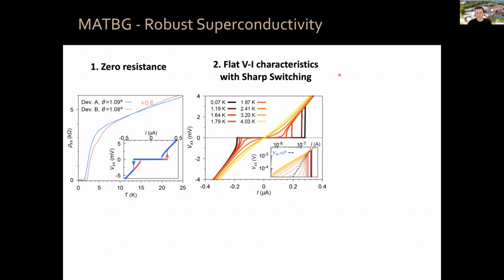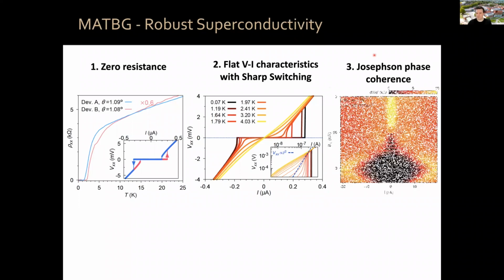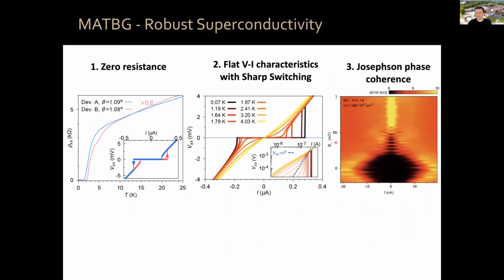And then the last thing, which I think perhaps is one of the most important ones, is that you should look for Josephson phase coherence. If you measure the critical current as a function of perpendicular magnetic field in these devices, because there is a little bit of disorder and you can tune the system close to the insulating behavior, you have a network of Josephson junctions which leads to Fraunhofer-like patterns of various types. Basically, the system exhibits Josephson phase coherence. I think that you need to show those three characteristics in order to claim robust superconductivity.